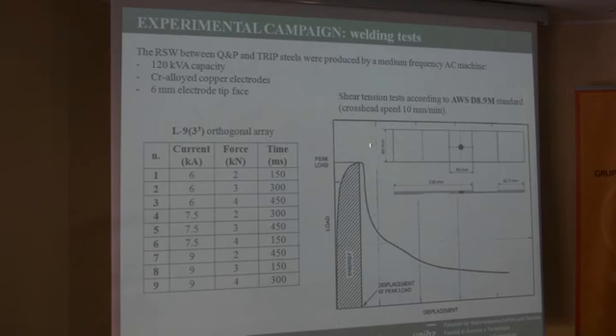Here you can see the size of the samples that were obtained after welding test. In particular, the samples were used according to this AWS standard, which is the reference standard for an evaluation of the mechanical strength of resistance weld spots. In particular, the results obtained from this test are represented by the maximum peak load reached during the test, that consists in a traditional tensile test, and the area that you can find under the curve up to the peak load. And these are the two main important pieces of information that can be collected by this test.